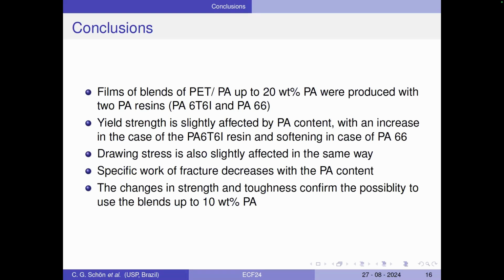And if we combine the two things, we could come with the conclusion that we shouldn't add more than 10% PA in this blend. Just to give an information for you, we did the barrier test, and this film is really better for barrier of oxygen.